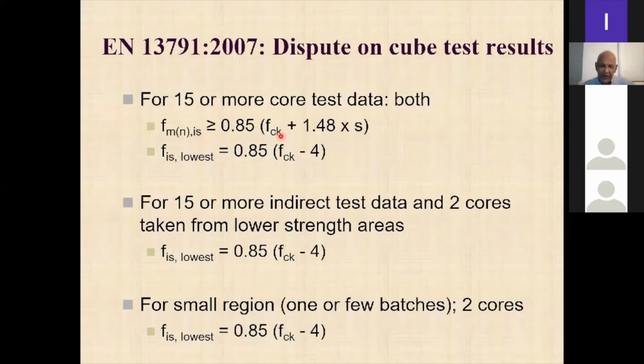Let us say if it is a grade 25 concrete, then you find the standard deviation from this. Then the in situ strength should be greater than or equal to this value in order to accept the concrete. And in addition, the lowest in situ strength that you get should not be lower than this. Then you can say, well, the concrete that was delivered by the supplier, in fact, has this fck value.